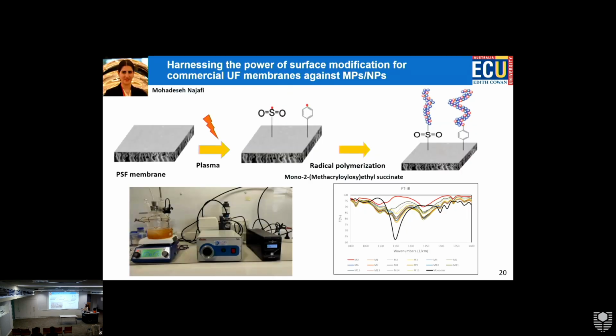So in this one, Muhaddasa, who is here as well, did a different approach. Until now, we were adding materials as nanofillers into the structure. In this case, Muhaddasa did graft polymerization, plasma-induced graft polymerization. Is anyone familiar with this technique? With the plasma-induced graft polymerization, we use plasma to activate the surface first. So in this case, she added carboxylic acid functional groups to the surface.